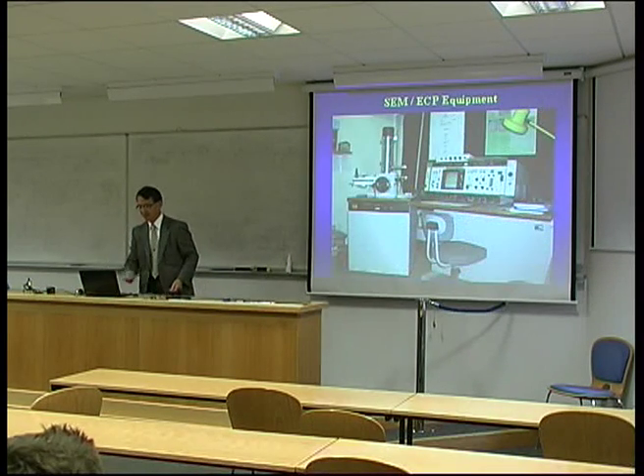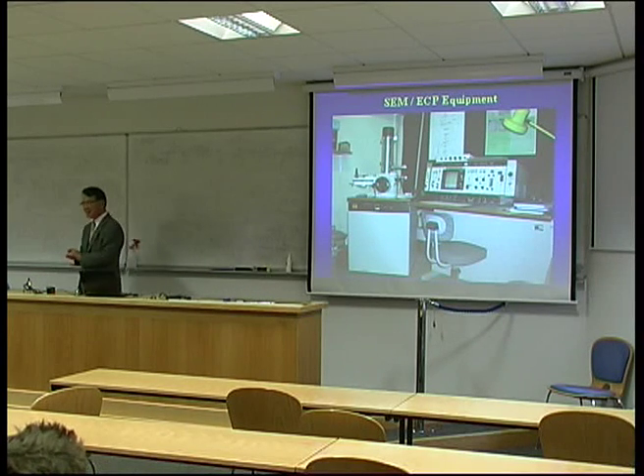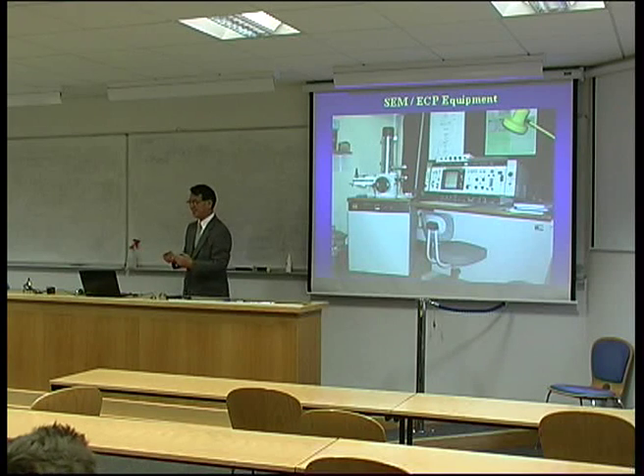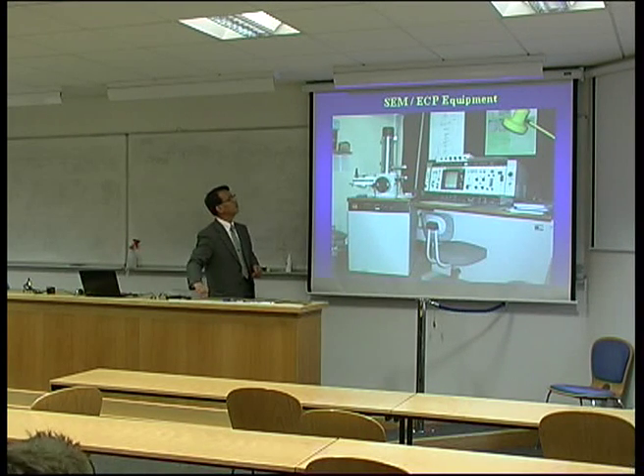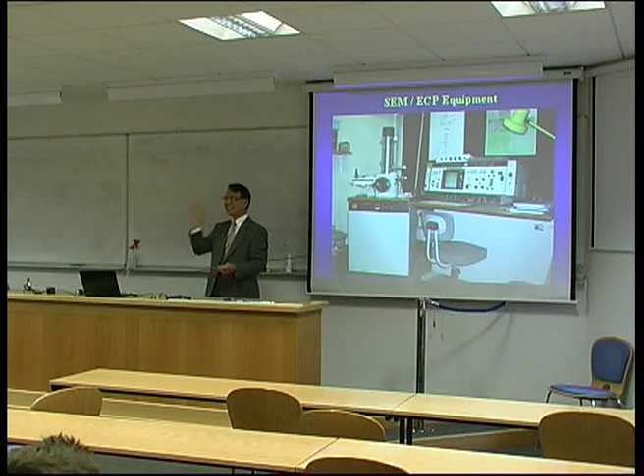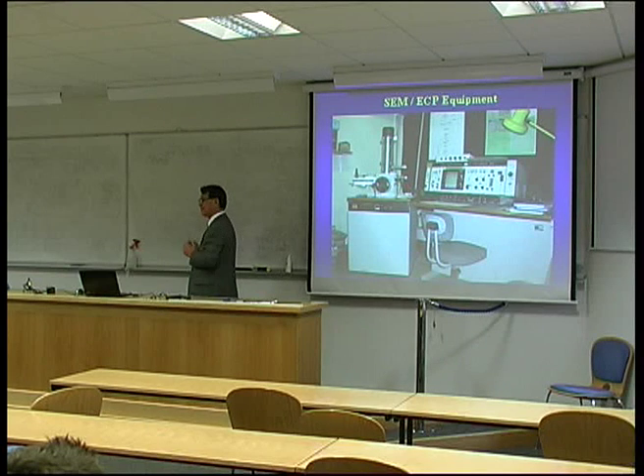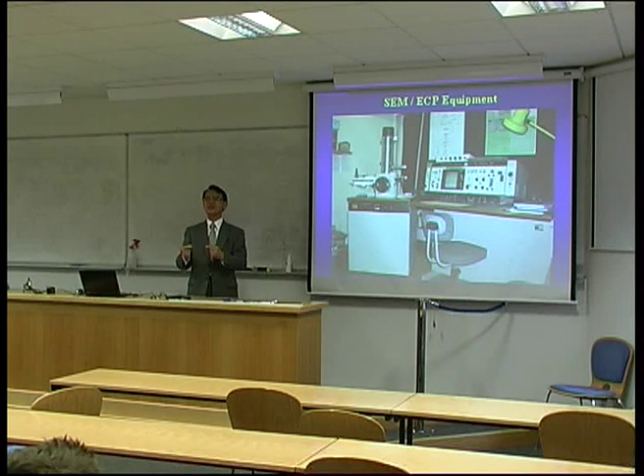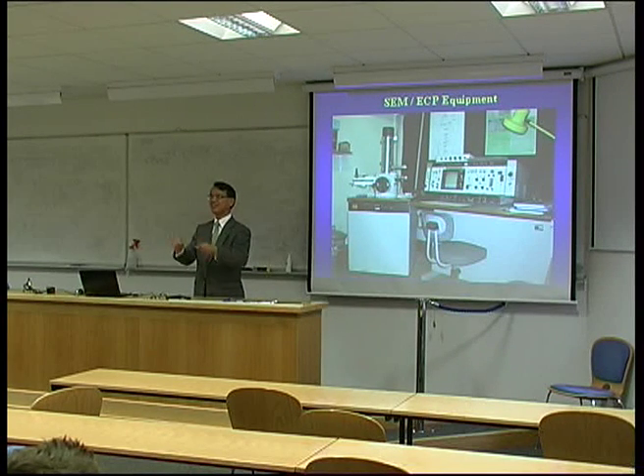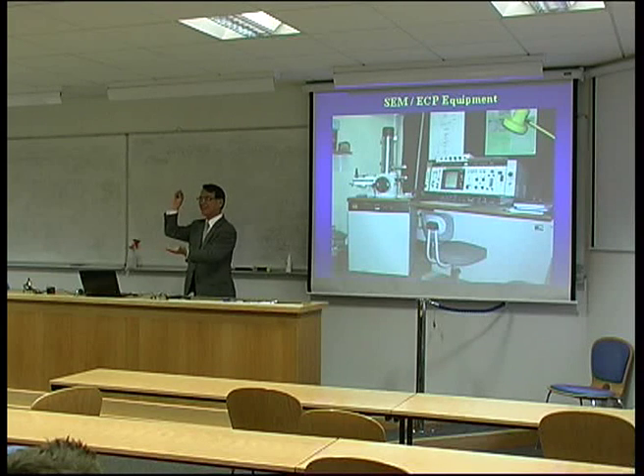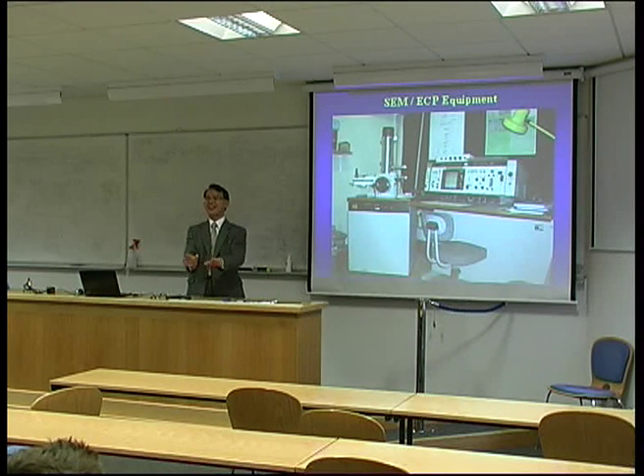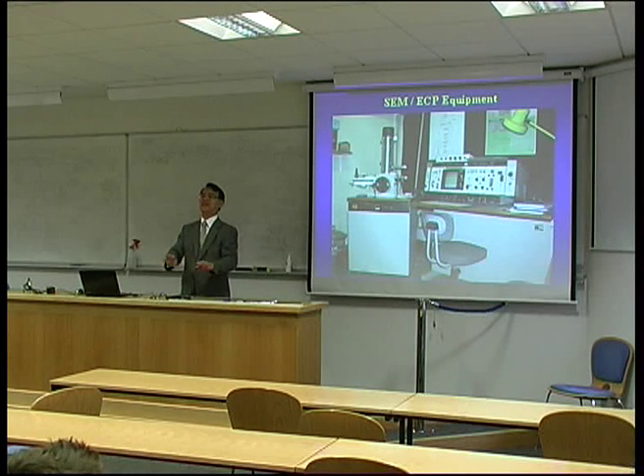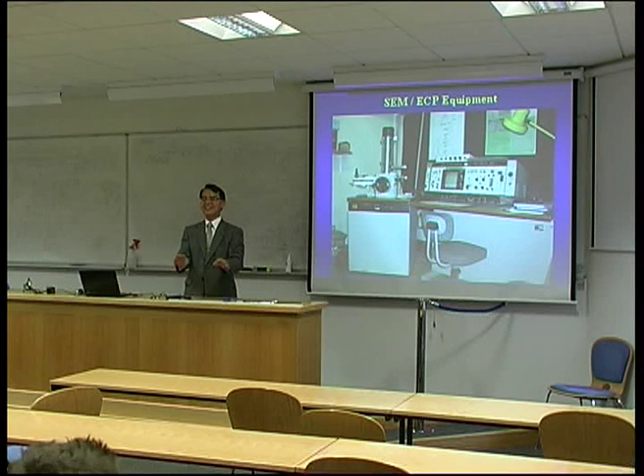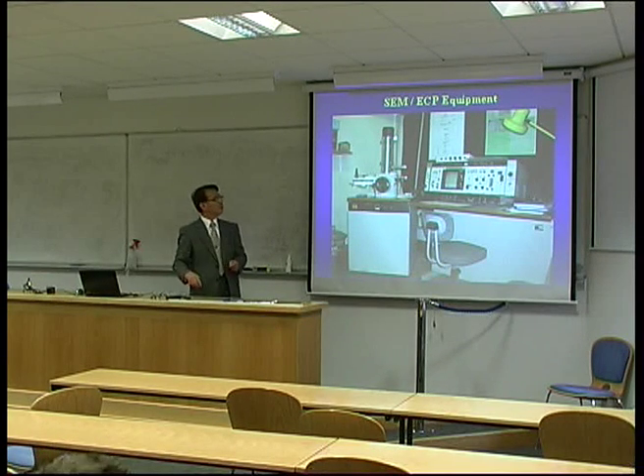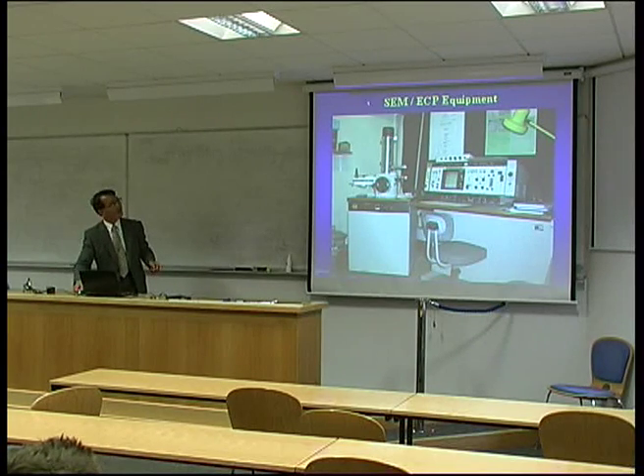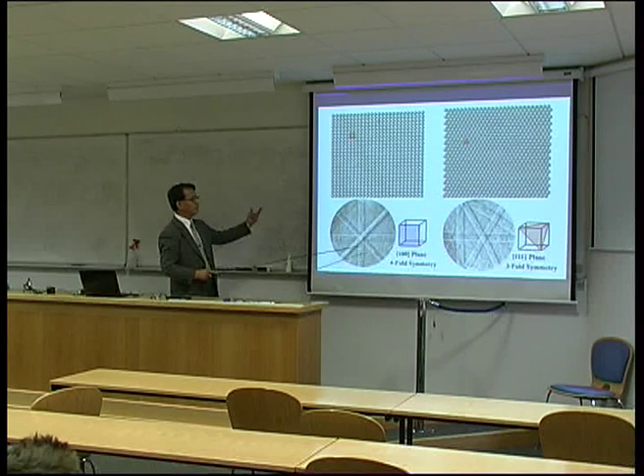Yes. But anyway, so nearly 30 years ago, to characterize the grain boundary, we used a scanning electron microscope equipped with electron channeling pattern. This was, at the time, the most advanced technique. But that means you had to spend so many hours to characterize by hand. First, you have to take the micrograph and then characterize the relative orientation by hand, maybe using some computer. Of course, later on, we used a large-scale computer, but anyway, by hand.